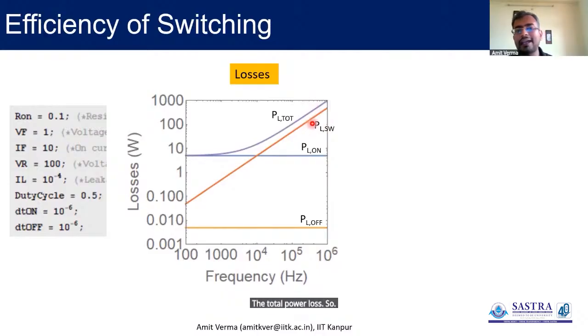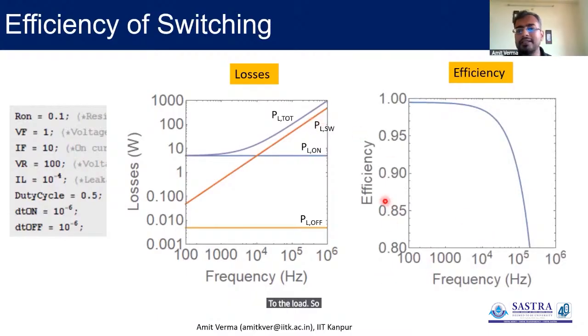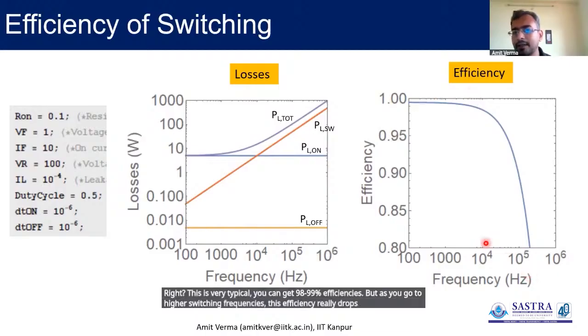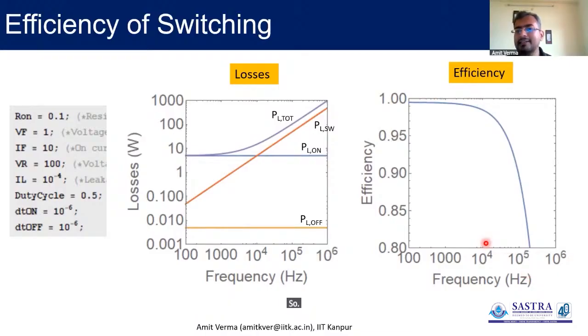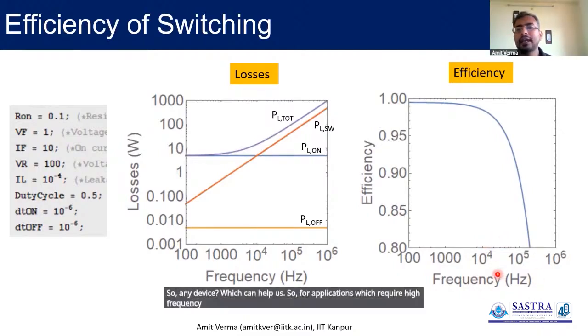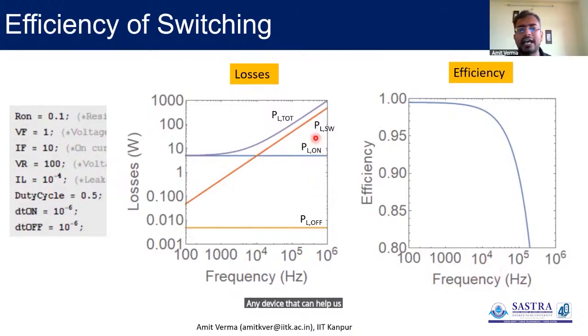So if we look at the efficiency of power transfer from the source to the load, at low frequencies the efficiencies are rather high, right? This is very typical. You can get 98, 99% efficiencies. But as you go to higher switching frequencies, this efficiency really drops. So for applications which require high frequency switching, any device that can help us reduce the dynamic power dissipation by essentially making a fast transition can really help in saving or improving efficiency at these frequencies.